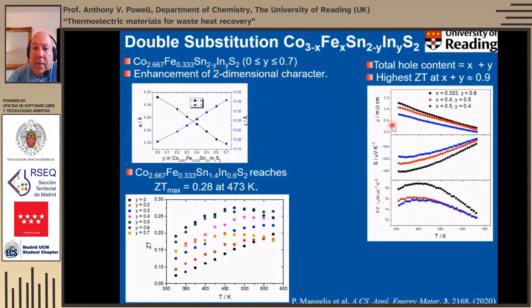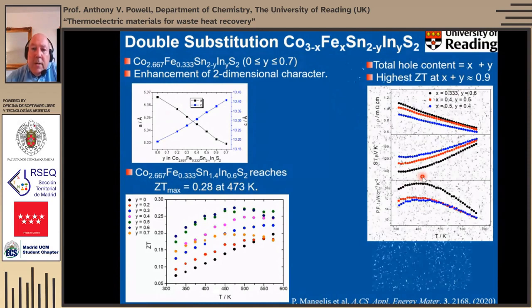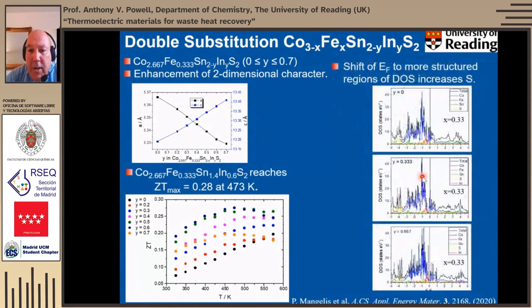So here are three different compositions with three different values of the iron content and the indium content, and you can see the properties are all quite similar. So there's something about that 0.9 hole content that is important. And from our band structure calculations, we find that what we're doing really when we go towards 0.9 is we're moving that Fermi level more and more into a highly structured density of states.